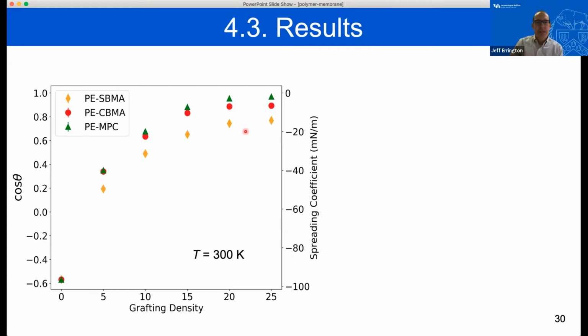The other thing to appreciate is that, similar to what we found before, the SBMA case has sort of the weakest impact. The CBMA and the new polymer that we're looking at here, MPC, have a stronger influence on the system.